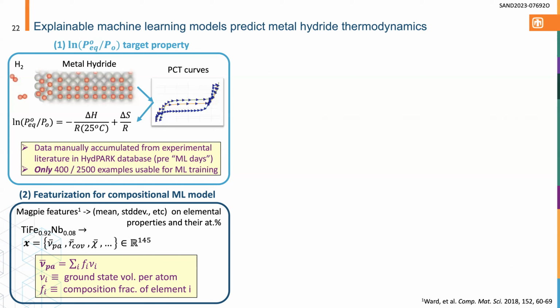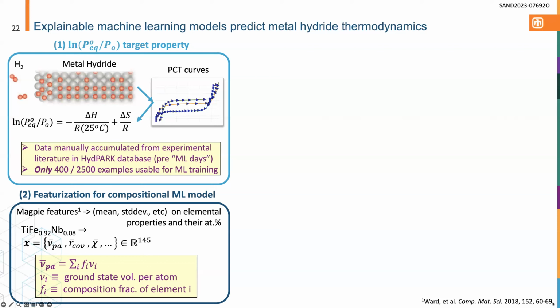The way that we went about building machine learning models is to build a simple compositional model based on MagPie features, by Logan Ward a couple of years ago, where you take the composition, take the elemental properties in that composition, and then take the elemental fractions, and derive a feature vector based on simple mathematical operations around those composition-weighted properties. As an example, I'm showing the volume per atom. That's the volume per atom of the elemental solids weighted by its compositional fraction. That's how you compute this new PA value, which I'll reference a few times.